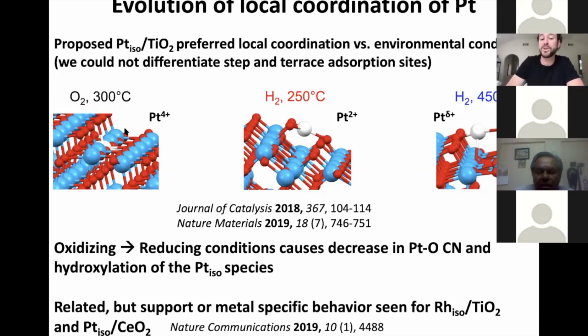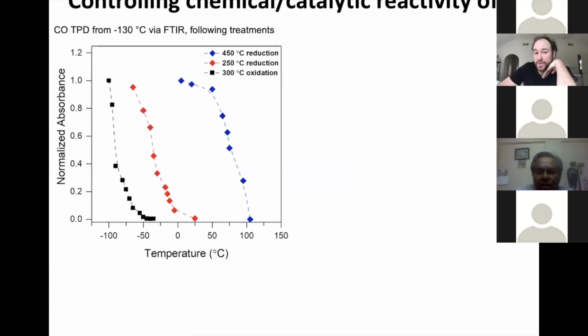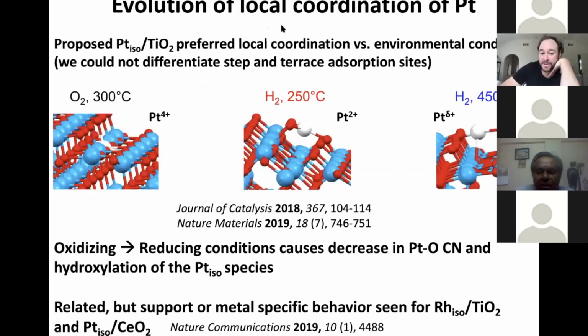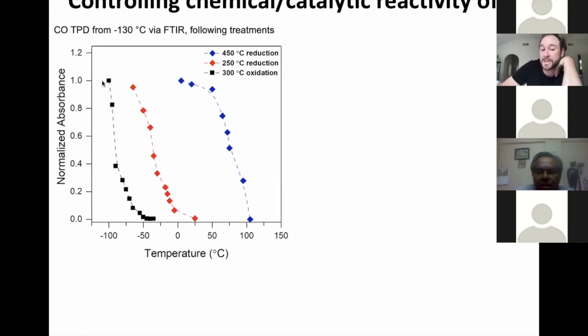So this is to tell you that the coordination environment of these platinum atoms on the support can change. And this will happen as a function of the environmental conditions you operate under. We also showed that when you do analysis of the reactivity of these samples in these 3 different coordination environments, they have very different reactivities. So if you do a CO TPD, CO will come off the more oxidized site at much lower temperatures than it does off the more neutral platinum atom that was now just bound to 1 or 2 oxygens and was hydroxylated. So inherently its reactivity is different.